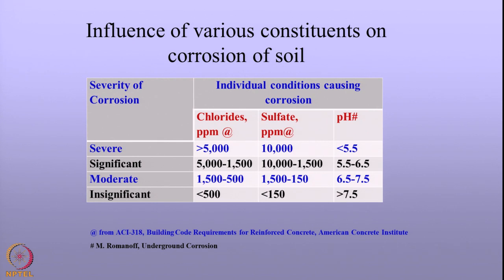Coming to the soil again, the chemistry of the soil decides the corrosivity of the soil. Three factors are given here: one is the chloride content of the soil, the sulfate content of the soil, and the pH of the soil. As you notice, between chlorides and sulfates, generally the chlorides are more severe, more corrosive as compared to the sulfates. In both cases, however, if the salt concentration increases, the severity of corrosion increases.